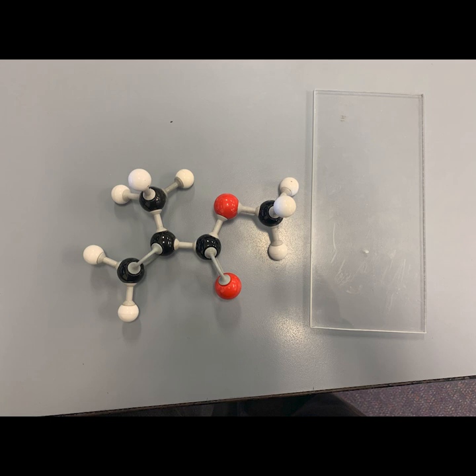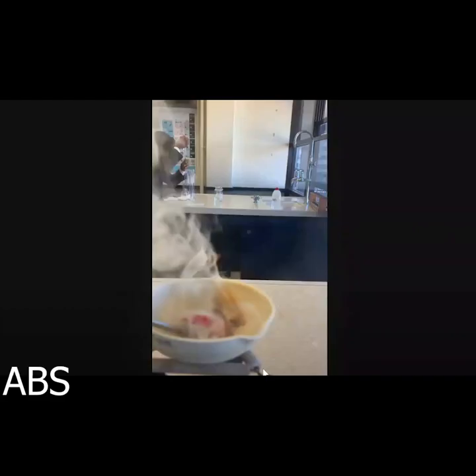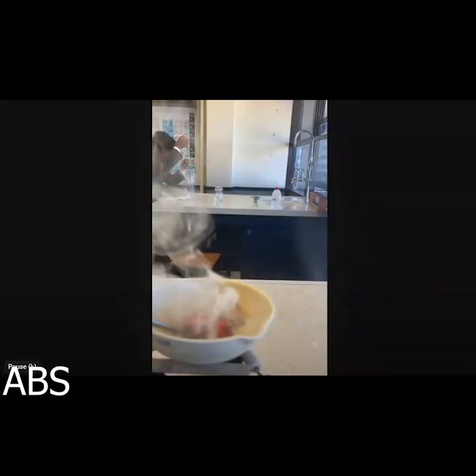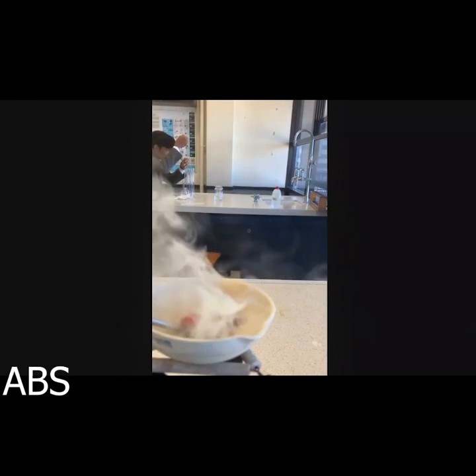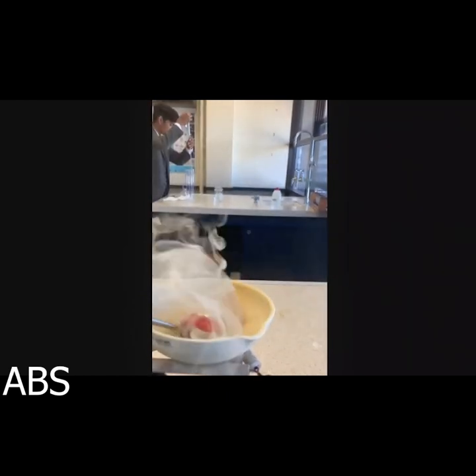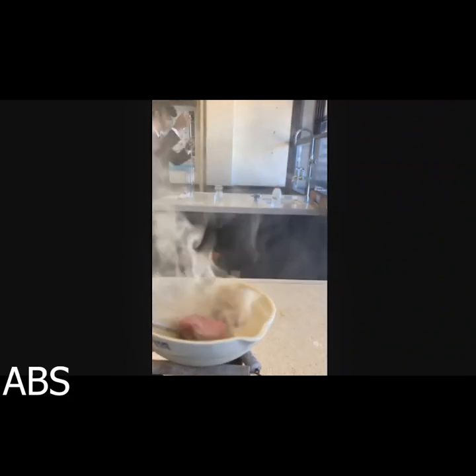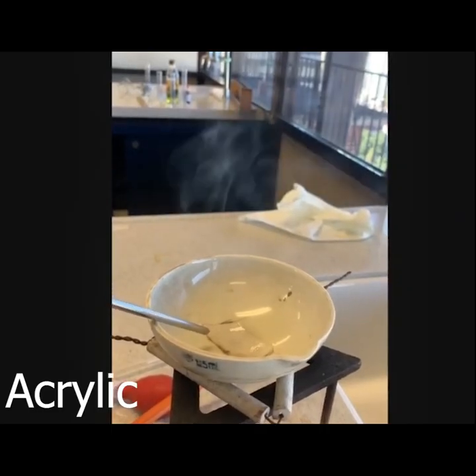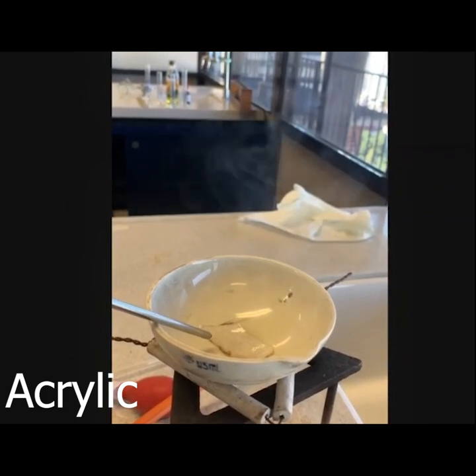For both polymers, the hydrogen bonds increase the boiling and melting temperatures when compared to similar-sized molecules without the hydrogen bonding, requiring more energy to counteract the force of the hydrogen bonds. This is seen with the results of the demonstration. The ABS began to soften at 111.4 degrees Celsius, whereas the acrylic began to soften at 133 degrees Celsius.